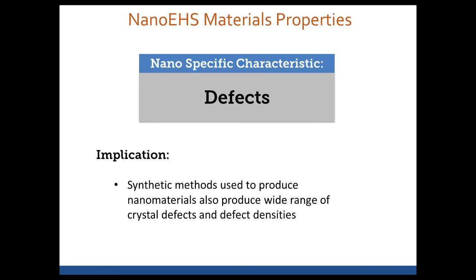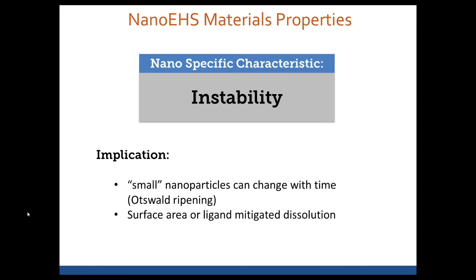And then one more is defects. We've got synthetic materials that can be influenced by having an impurity in them, and that impurity can actually lead to the last one, which is instability. Here you can have these small particles that can change with time, and again, this is another concept that isn't usually seen in the bulk field, where due to the curvature of the particles, they can release ions, and the particle size distribution can change with time.